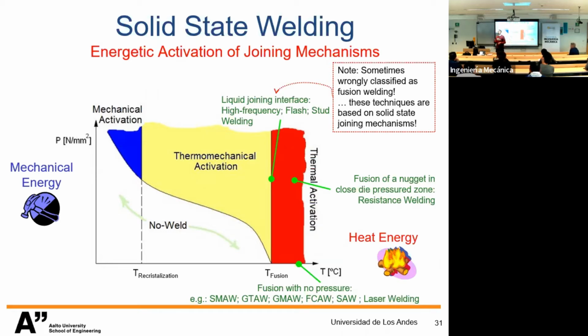So there are two ways to generate these chemically active surfaces, new surfaces that are looking for a new energetic balance, and if we bring the materials together, we can then activate the atomic bonding and diffusion that are going to happen. So we can make it by bulk plastic deformation or by liquidification and projecting out the liquid zone, leaving behind the chemically active surface.